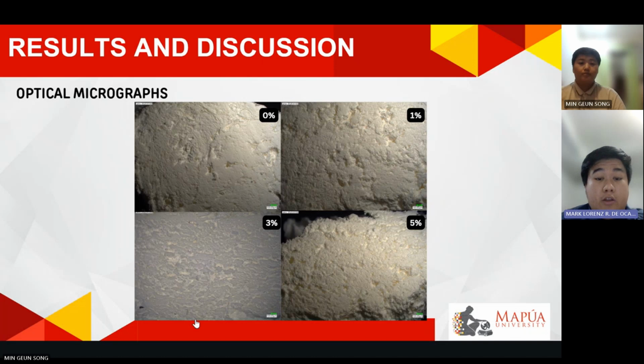As the concentration of the SM-NPCC increases, we can see a noticeable increase in surface roughness. The composite surface becomes more irregular, indicating the effect of the surface-modified NPCC integration into the PLA matrix. These surface irregularities are primarily attributed to the integration of the surface-modified NPCC particles within the PLA matrix. The particles create disruptions in the material structure, which is evident in the micrographs. Next.